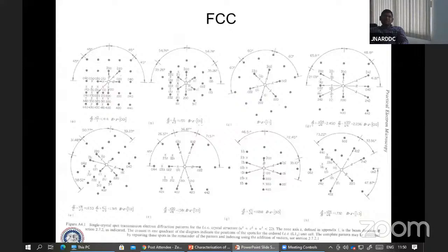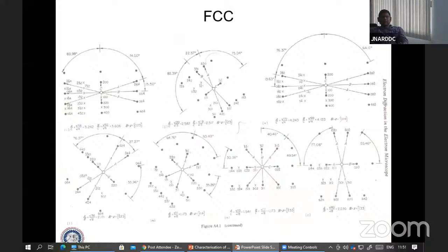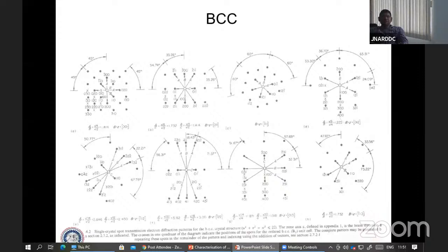And one more condition is that it has to also satisfy the Weiss zone law. So after getting all these HKLs, H1, K1, L1, H2, K2, L2, we have to cross check with this UVW. This is a zone axis. So Hu plus Kv plus Lw should match with 0. Then your indexing of this diffraction pattern will be correct. So there are some 19 diffraction patterns here. This is for FCC, and the same will be for BCC.